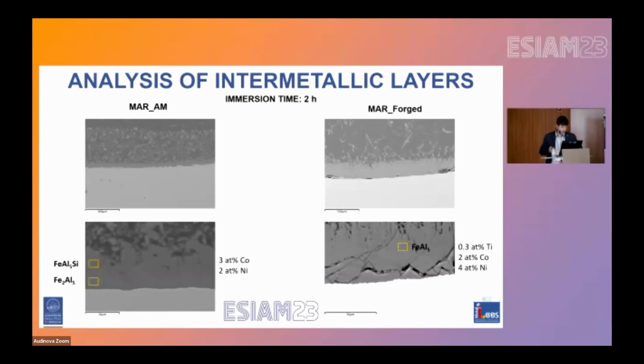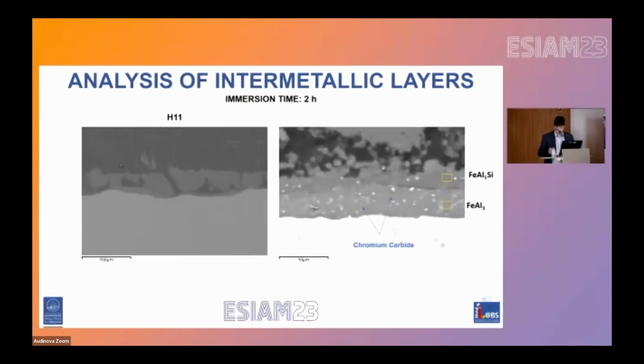Furthermore, the presence of more silicon in the intermetallic layer of the AM samples could be responsible for the reduction of the interdiffusion of iron and aluminum atoms with respect to the forged samples, promoting higher corrosion resistance. Also, the different quantity of the alloy elements can influence this parameter, thus promoting the superior corrosion resistance of the AM sample.